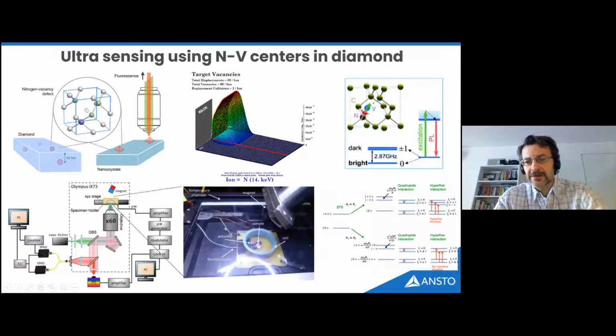Next slide, please. From here we went further, and as you know, the nitrogen-vacancy complex in diamond is a very interesting defect because it has a special property, and it behaves as a quantum center because we can distinguish different states. By producing nitrogen vacancies, we can create a large concentration of this type of defect in the material. When we place nitrogen vacancies in an ambient where we have a magnetic field, then we have a splitting between different states.